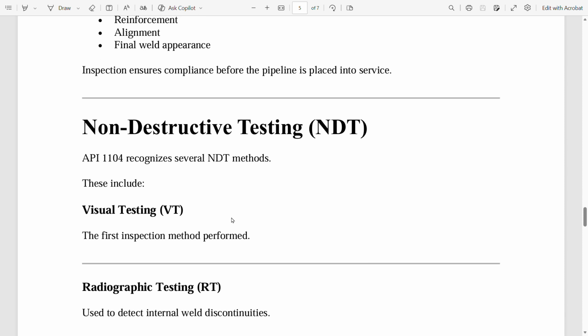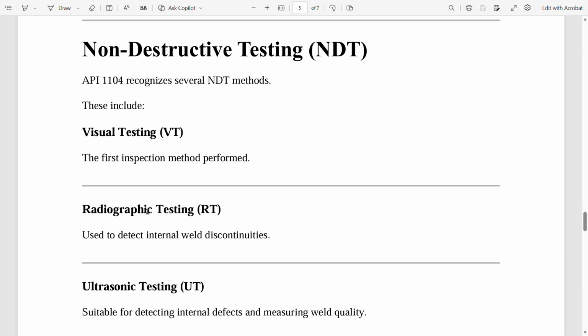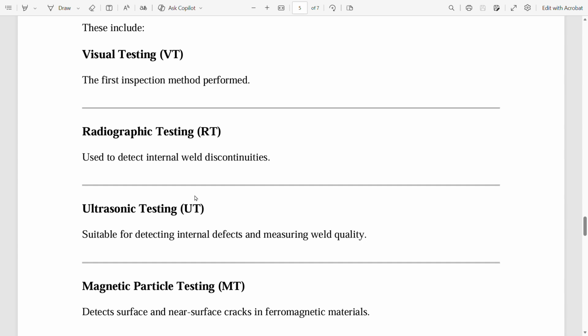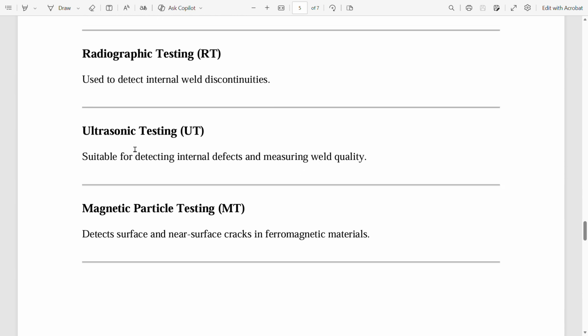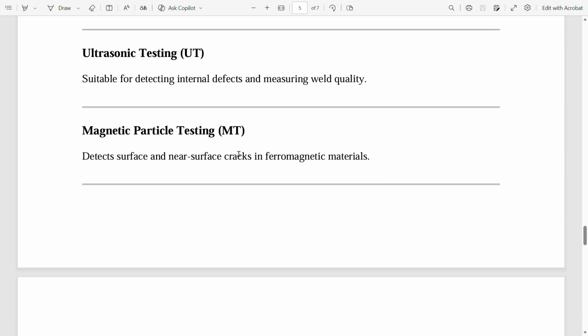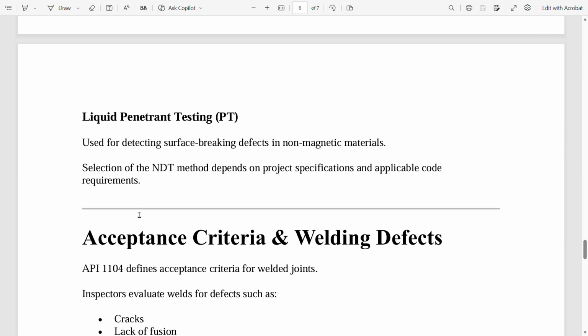Non-destructive testing (NDT). API 1104 recognizes several NDT methods. These include visual testing (VT), the first inspection method performed; radiographic testing (RT), used to detect internal weld discontinuities; ultrasonic testing (UT), suitable for detecting internal defects and measuring weld quality; magnetic particle testing (MT), which detects surface and near surface cracks in ferromagnetic materials; and liquid penetrant testing (PT), used for detecting surface breaking defects in non-magnetic materials. Selection of the NDT method depends on project specifications and applicable code requirements.